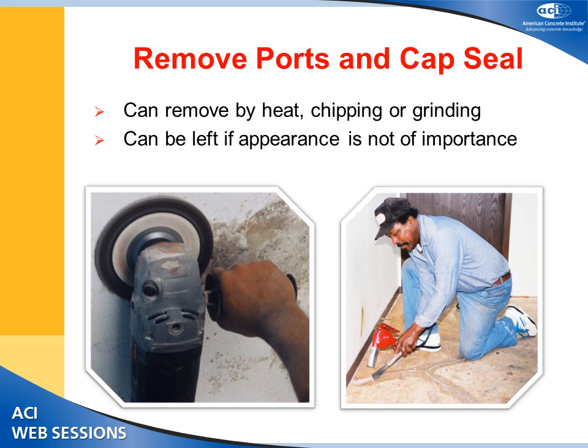Once epoxy injection is complete, ports can be removed by knocking them off. For a smooth surface finish, the epoxy paste can be removed by heating, chipping, or grinding. If aesthetics are not a concern in the area being repaired, the paste can be left on the surface — it will not harm the application, it is just an eyesore.